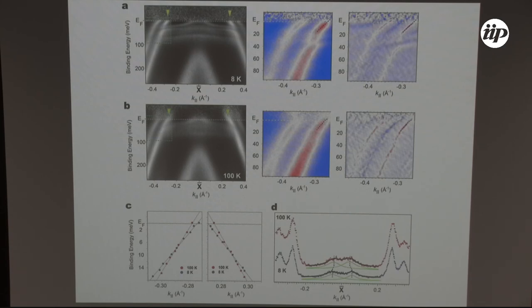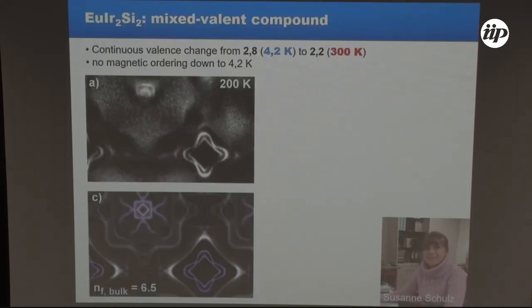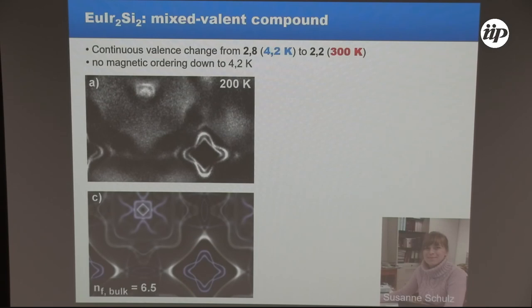At the same time, looking precisely at the neck for the iridium compound, we can detect with ARPES the signature of the change from large to small Fermi surface — the neck remains open but the transition is very smooth. For the rhodium compound we have not seen this; it may also be related to hybridization with the bandwidth. This issue needs to be clarified further.